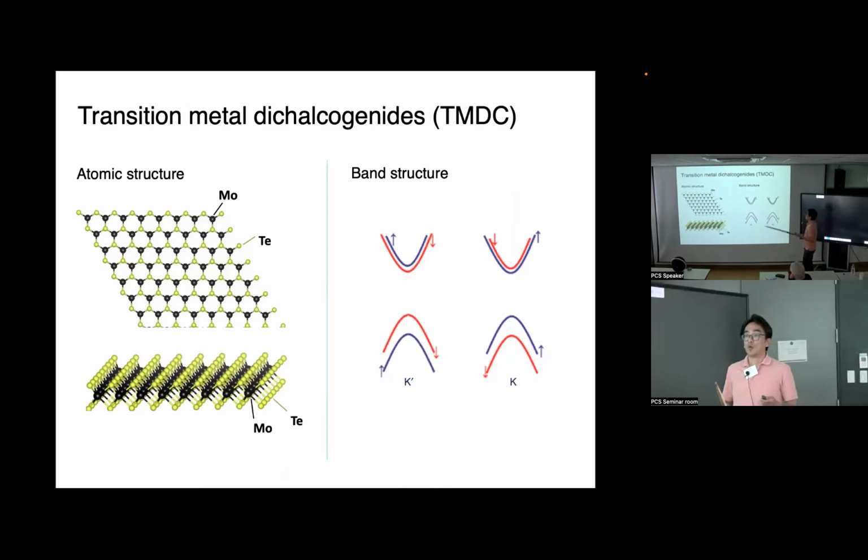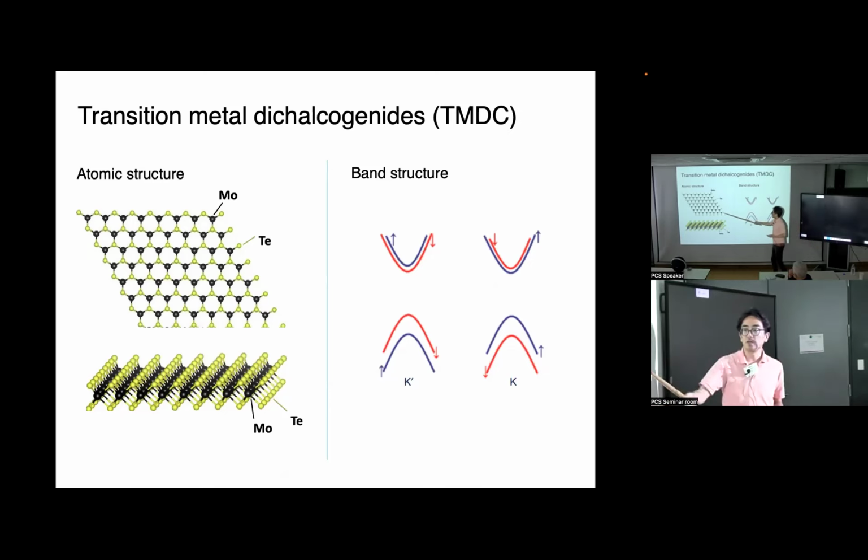Okay. So we also have a transition metal dichalcogenide Moiré structure. It looks like this. This is a 2D material, but it looks like 3 stories. And the band structure is very different from graphene. Now the Dirac cone is gapped. If you have a different sort of atom here, it gives a mass to the Dirac cone. Also, the molybdenum atom has a very strong spin-orbit coupling, so that we have spin splitting.